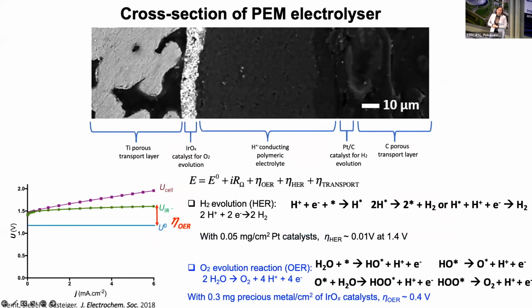Now, if we take PEM, for example, which is the most efficient one, and we look in cross-section, you will see that you have a bipolar plate, made of titanium, and then you have an iridium catalyst, and that is for the oxygen evolution. The oxygen evolution is the most important reaction. It happens under high oxidative potentials. It's quite corrosive. That's why you need metallic titanium and an iridium oxide catalyst, which is about the only thing that is mildly stable in these reactions.